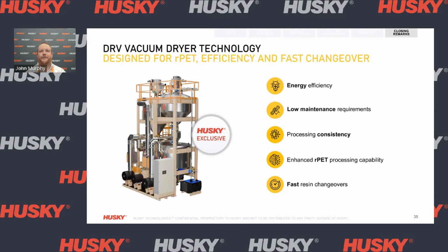And finally, we have fast resin changeovers. Due to the design of 4 distinct phases, a resin change can be completed in around 2 hours, compared to the 8 hours typically needed with desiccant drying systems. This has a significant impact on the overall equipment effectiveness of the system. All of these benefits work together to improve efficiency, consistency, and cost effectiveness when it comes to rPET processing.